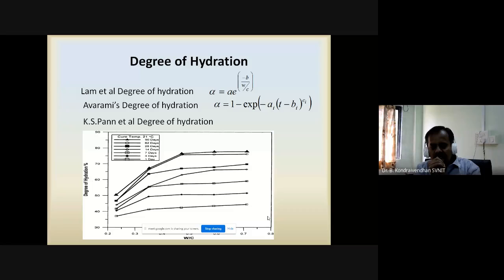First, we got Lam et al's degree of hydration. He has given the degree of hydration as an exponential function, with some parameters A and B. Again, it is a function of only water cement ratio. But actually, the degree of hydration is governed by water cement ratio and curing age. Whatever Lam et al has given is a function of only water cement ratio, so it is restrictive. So we cannot use it.